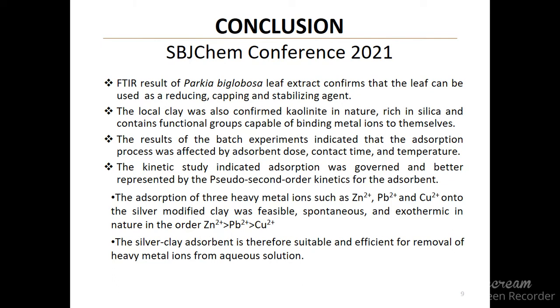From the other results, it can be concluded from the FTIR that the leaf extract can be used as a reducing and stabilizing agent for the synthesis of nanoparticles. Also, the local clay used was confirmed kaolinite in nature. Results of the batch adsorption indicated that contact time, temperature — at 30 degrees — affected the rate of reaction, and the kinetics also shows a second-order reaction. Finally, the silver clay adsorbent is therefore suitable.